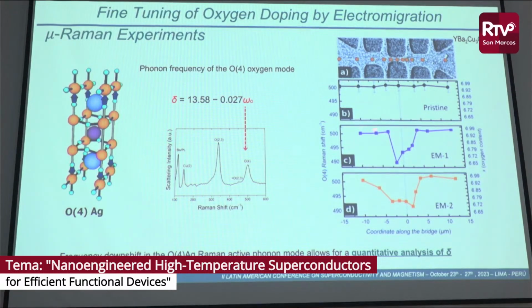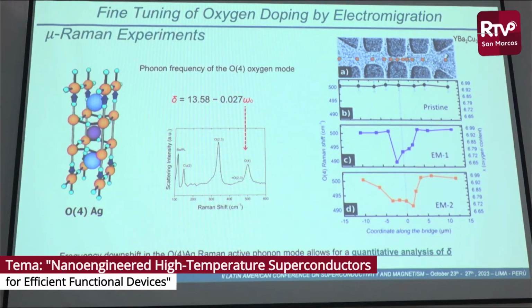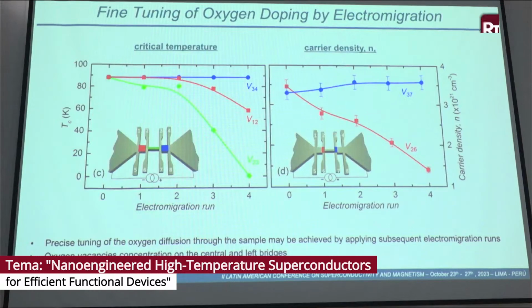What we see here is that this oxygen position shifts, and we have this dip here in the amount of oxygen that is enlarged when we introduce a higher electromigration run. So with this, we can track and have a quantitative analysis of the delta and thus the doping of the system. And we can build this kind of graphs, TC as a function of the electromigration run, and the carrier density also as a function of the electromigration run.